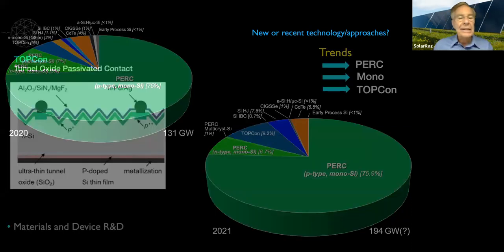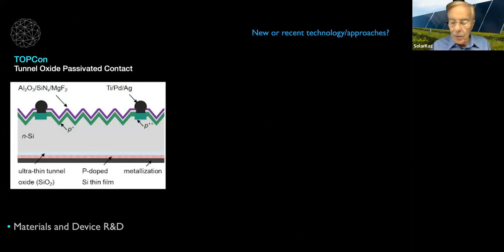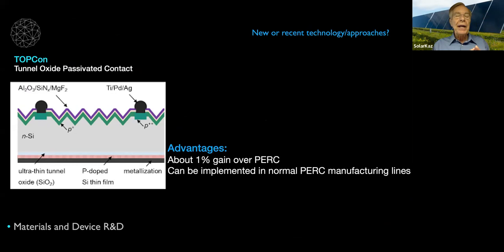And this is the TOPCon cell. You can compare it to what it looks like for the PERC technology. They look very, very much the same with a little bit of change in the structure. They were able to adjust the physics a little bit. And basically, with the same sort of manufacturing, you get about a plus 1% gain in the efficiency. This means if your cell was 25%, it is now 26% without doing anything to your manufacturing line. And that's why people are going to this, because, hey, efficiency is king in the photovoltaic world.